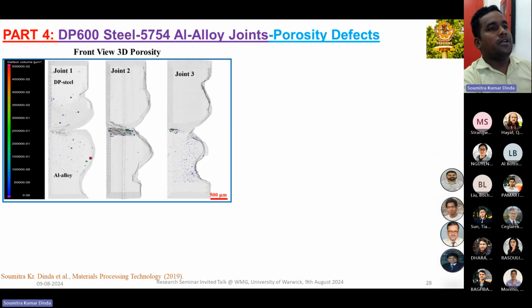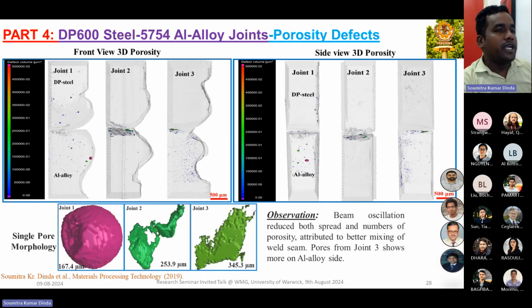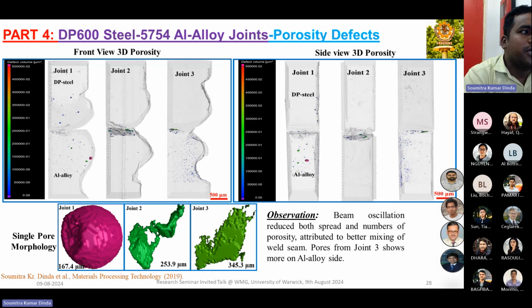Now let's see, similarly to what we did for the porosity defects. Again we find that the top portion is the DP steel and the bottom portion is the aluminum alloy. We found that the porosity is formed extensively on the aluminum alloy side, compared to the steel side of the joint.